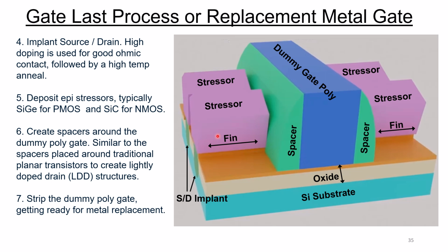Step number 6 is to create spacers around the dummy poly gate, and that's these two green regions here. And these are created in a similar manner to the spacers placed around traditional MOS transistors to create the lightly doped drain LDD structures. And the 7th step here is we actually strip out the dummy poly gate, which is this blue region in the middle here. And that's getting ready to replace this dummy poly gate with metal.